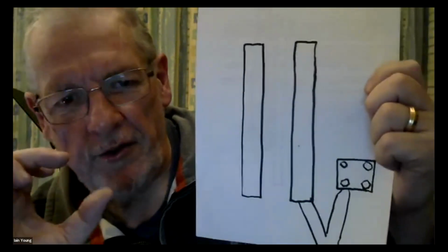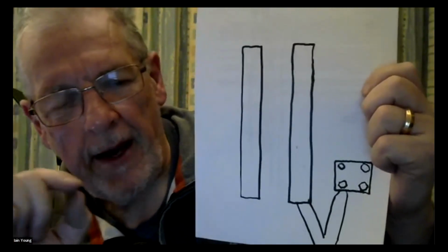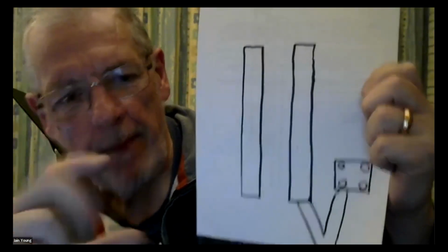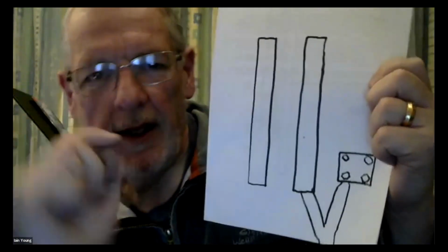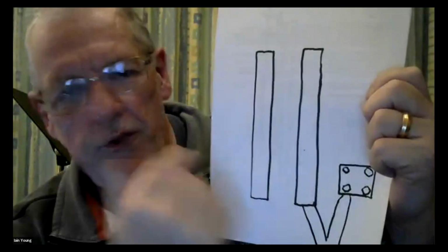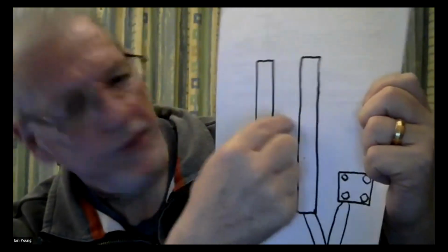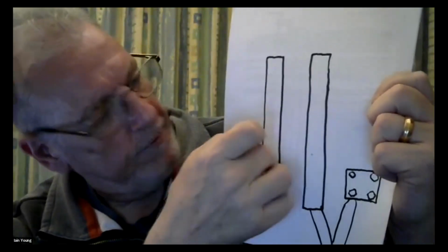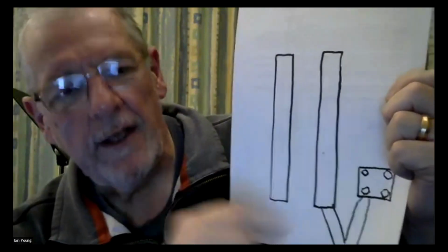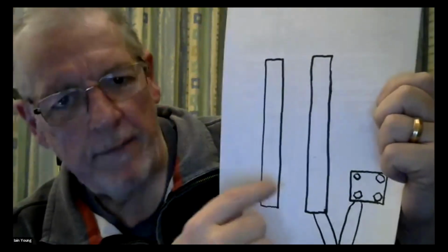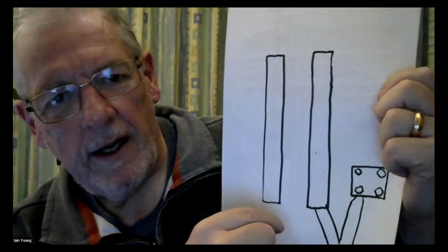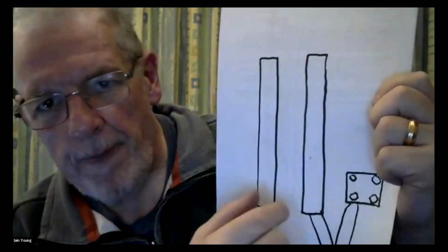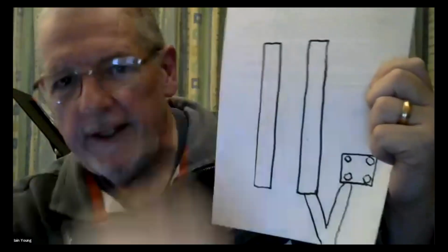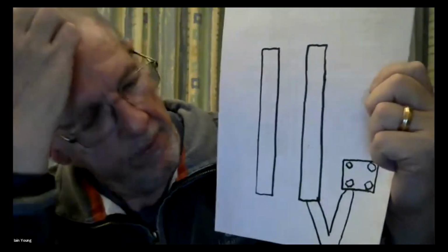I've done some Great Western Station and yard lamps, and we've made them hollow. But because they're quite tall, even this didn't work. The metal would go in, it would fracture the plaster in the middle, and you'd end up with a hole in the side of the casting. So initially we tried making a mold by putting brass tube in, because we wanted hollow to put the LED through there.